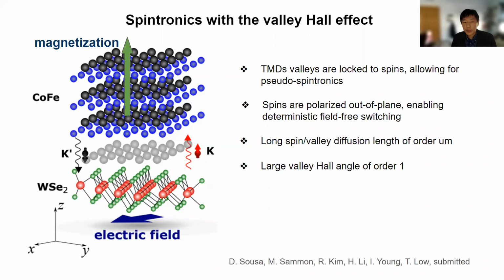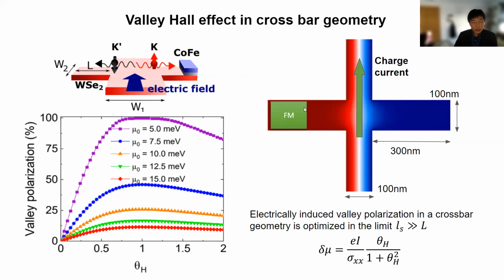Another quality of this transition metal dichalcogenide is the long spin-valley diffusion length, of order 1 micron, which allows the spin to diffuse a much longer distance compared to a lot of the spin Hall materials. And also the valley Hall angle has been shown to be larger than 1. So this all points in the direction that this might be a good material for spin Hall devices. So we look at the device structure as follows.